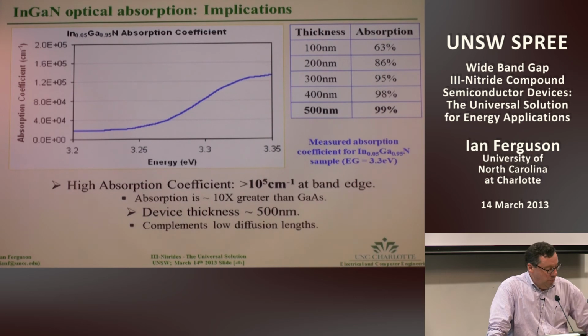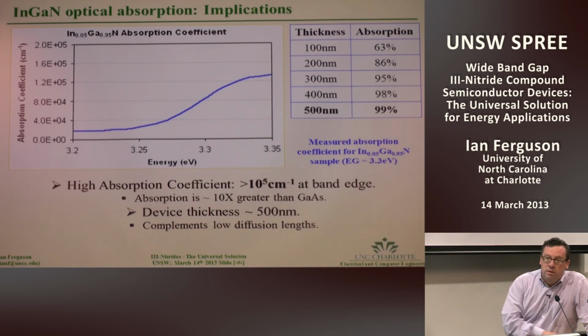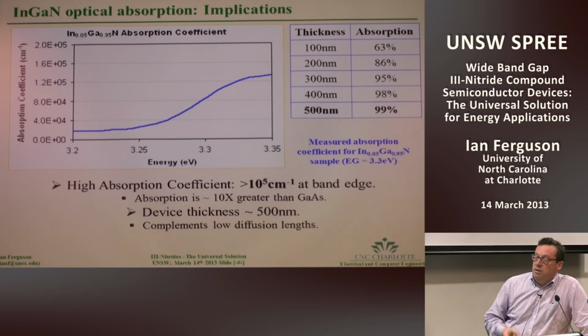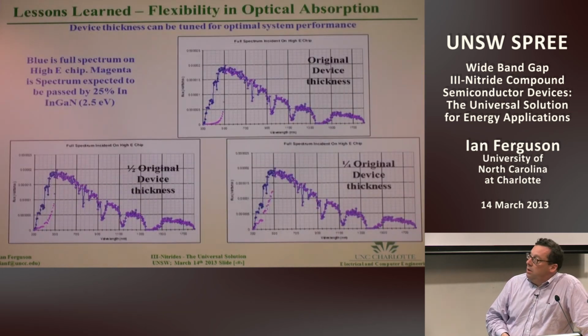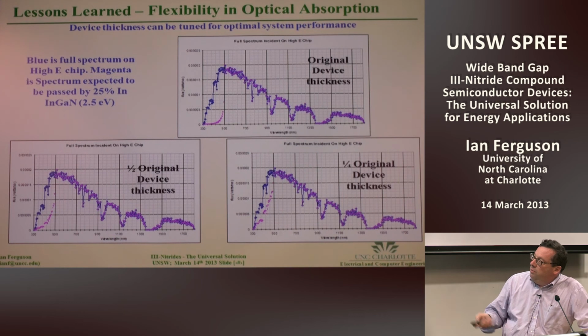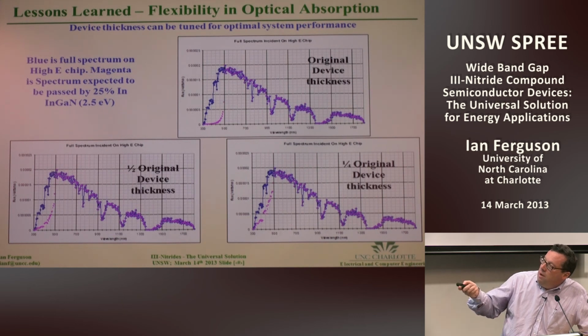So you put in these centers, so you're still trying to hold the material together, and about two orders of magnitude higher doping concentrations than your free carriers within the material. So your p-type doping is typically low, 10 to the 18 in these layers, unless you start doing things to control this. And this is just showing some of our original devices when we went back and modeled it.